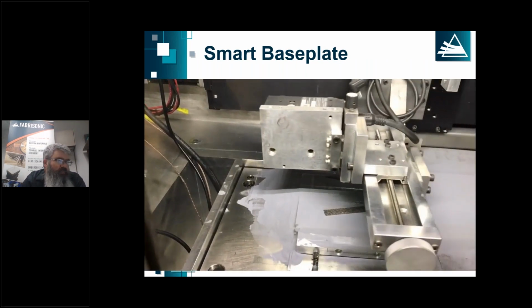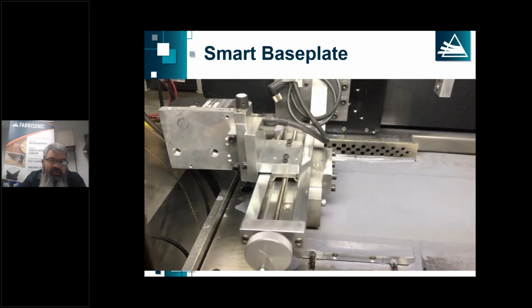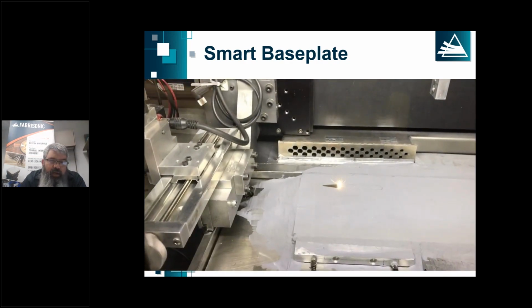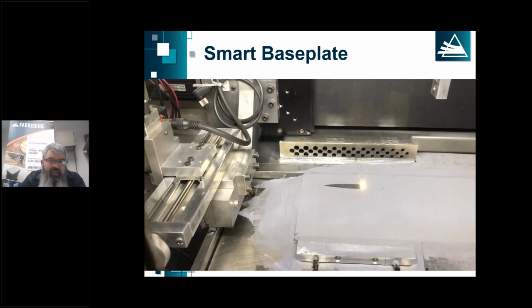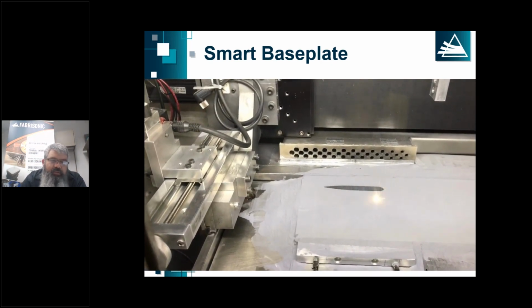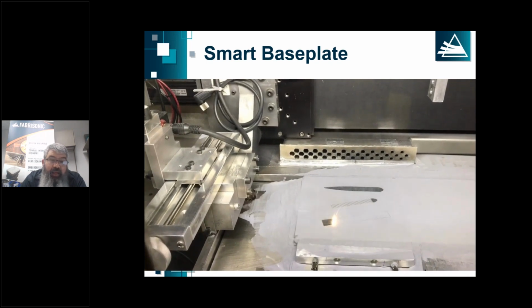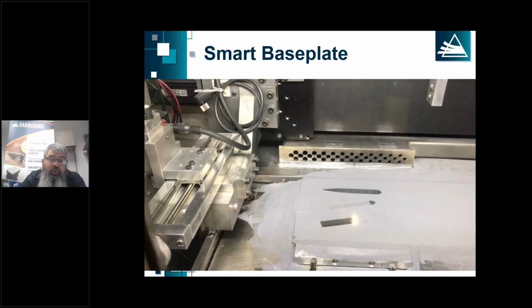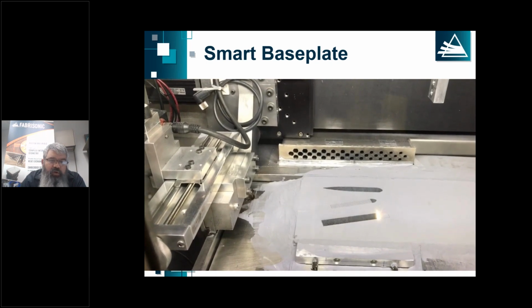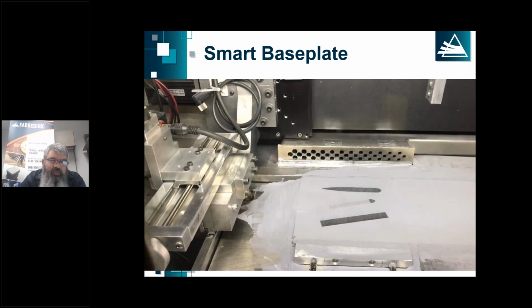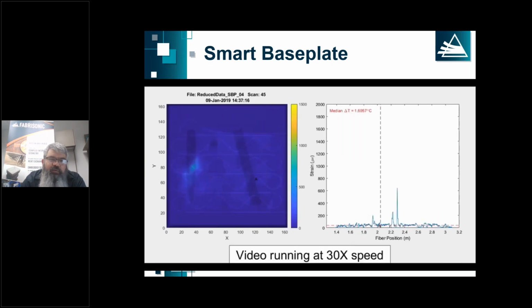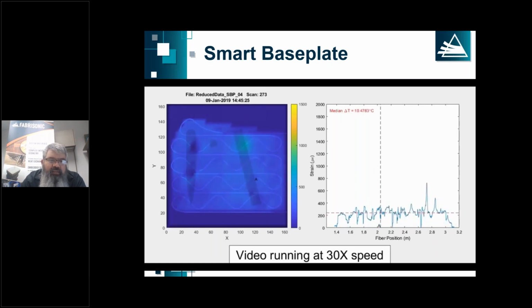This is a custom powder bed system at Edison Welding Institute. But at the bottom, you can see some black wires. Those are actually our embedded sensors coming out of the build plate. So throughout this print job, we were able to get data live on the fly of both strain and temperature as this build evolved. And that allows us to do a lot of quality monitoring as well as looking for defects. So on the right-hand side, you're seeing the actual magnitude of strain along the length of a fiber optic cable. On the left-hand side, you're seeing magnitude of strain via color.